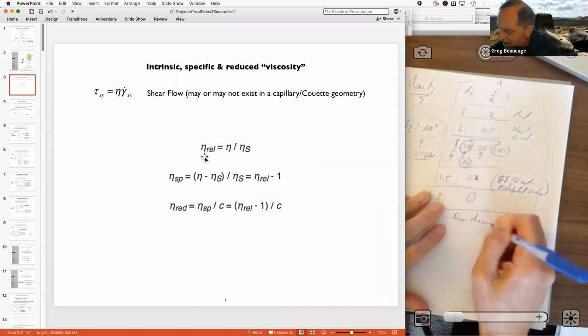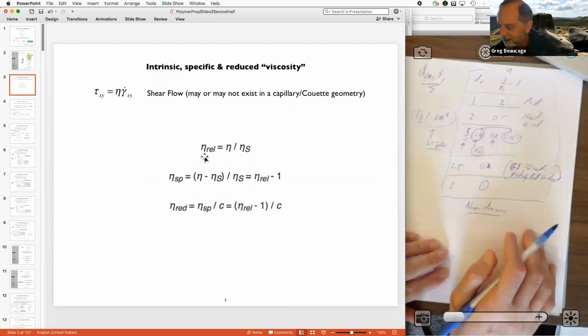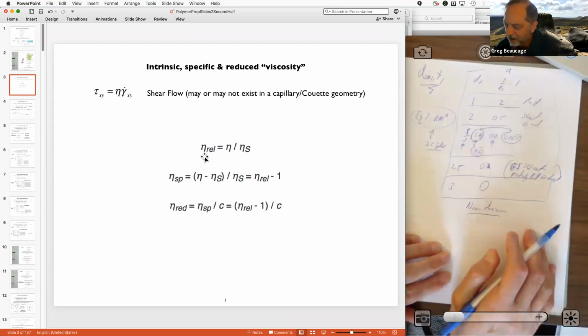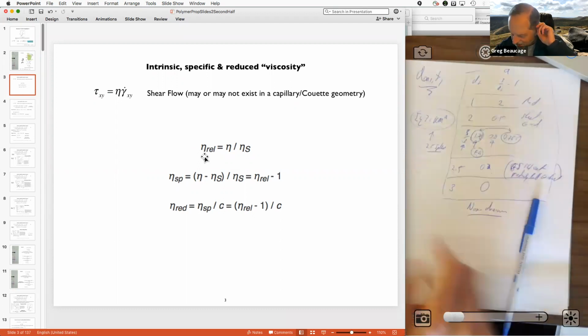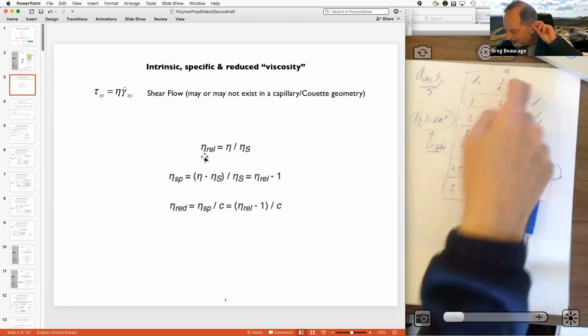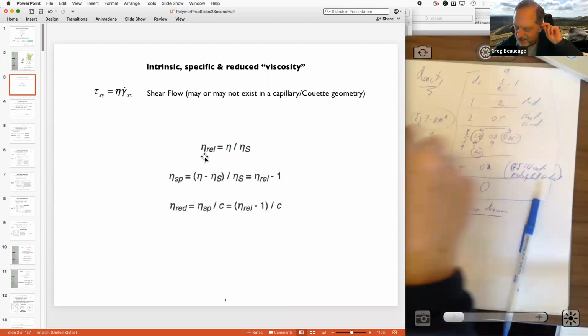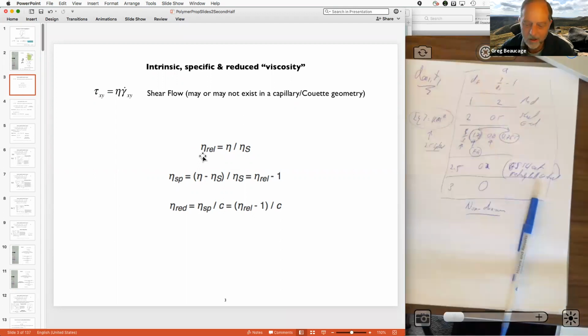So if it's draining, then this whole thing becomes muddled, right? So it depends on how the solvent drains from the chain. All these numbers will change. So basically, you get some number for A in a given solvent at a different temperature, and then you can map out the molecular weight just using this capillary viscometer.